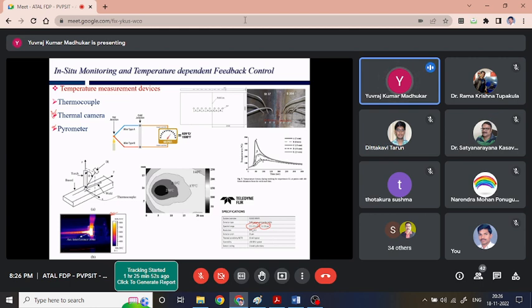In this image, we can see the data I got from one of the player companies. Here we can see the spectrum through which it is taking the radiation is very broad: 3 micron to 5 micron, in another case 1.5 micron to 5 micron. The broader the spectrum, the more the result is going to be averaged. For example, at this point in time, possibly the temperature is showing 800 degrees centigrade. Here the blue color is showing nearly 350 to 400 degrees centigrade. Ultimately it is giving the relative temperature distribution around the position.